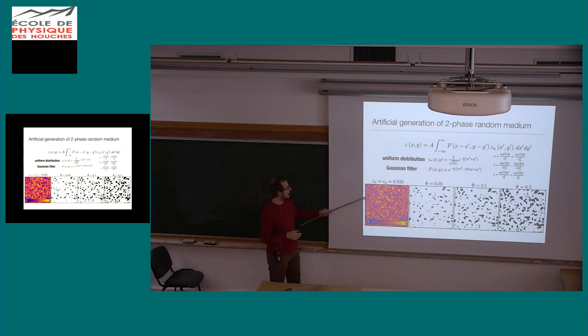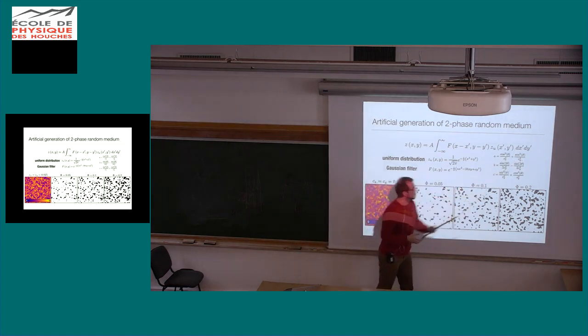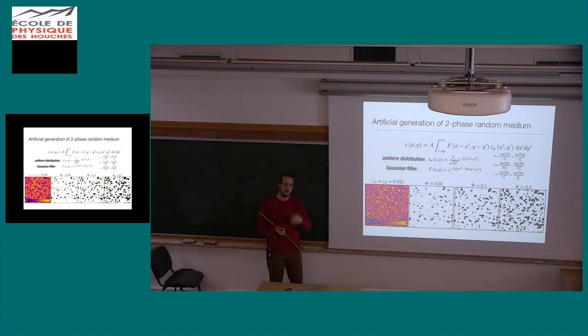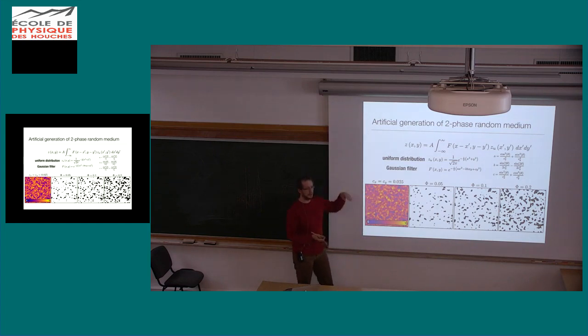So what I do is, I create a random correlated Gaussian field here. It's basically like creating a topography where you prescribe how far, on average, for example, all the hilltops and the valleys are apart. This is then the Cx and the Cy, which are the correlation lengths in the x and in the y direction. So you basically prescribe how far they should be apart, and this is the structure. You can also add an angle to that, so that things get rotated.